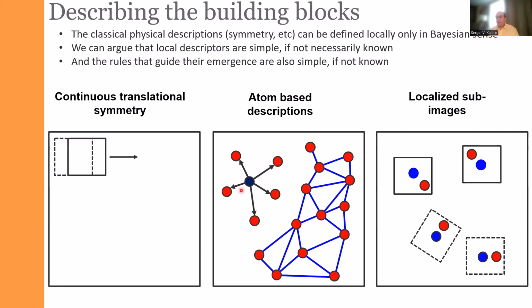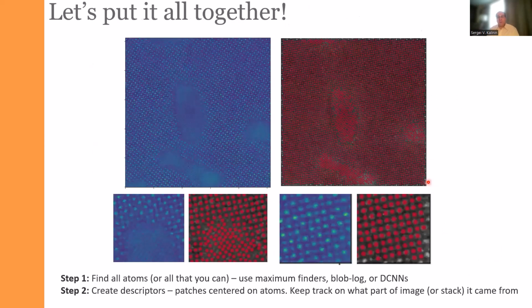Sometimes we come up with integrated approaches. So for example, if we take the atomically resolved image and transform it into atomic coordinates, we basically throw out all the information associated with the contrast within the image. So sometimes we use the atomic positions or grain boundary coordinates, whatever, as anchor points for selection of patches on the image. But generally, for the time being, the primary type of image encoding we worked with is patches.